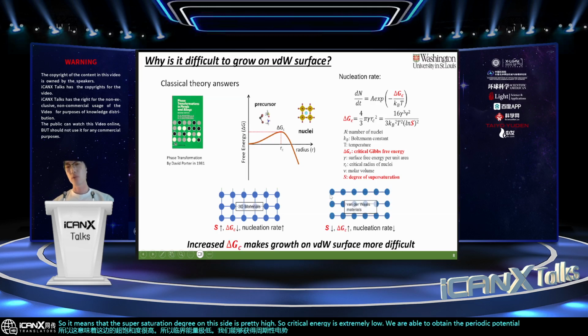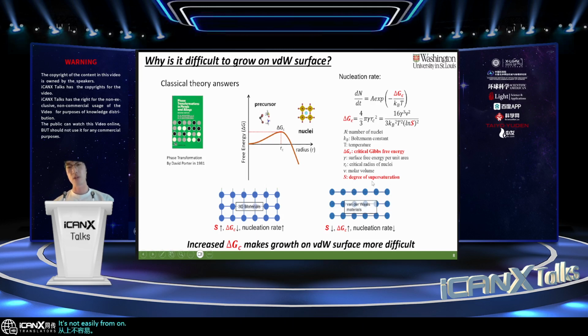On the other hand, the van der Waals terminated surface is exactly the opposite case. The orbitals are already fully saturated, so the supersaturation degree is extremely low and the critical Gibbs free energy is high. So nucleation is not easily formed on the surface because it's thermodynamically already stable. So to make growth of single crystal material happen on this van der Waals terminated surface, we need to decrease the critical Gibbs free energy again.